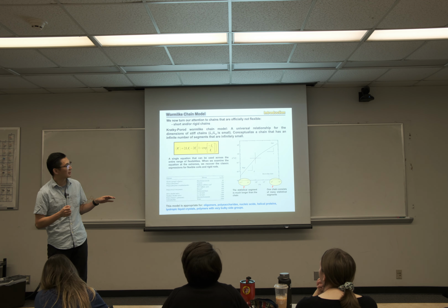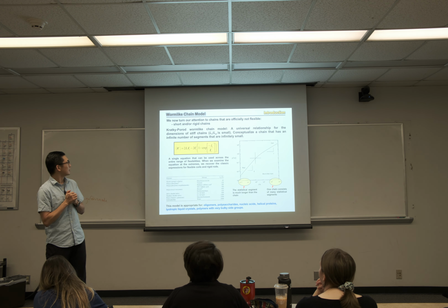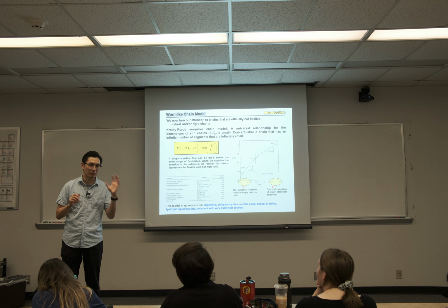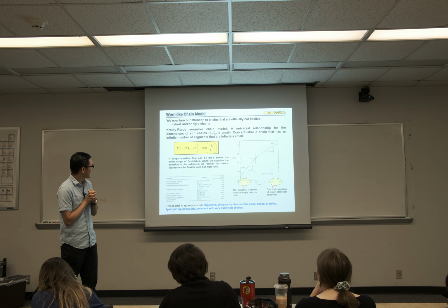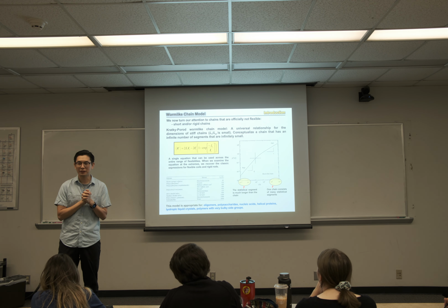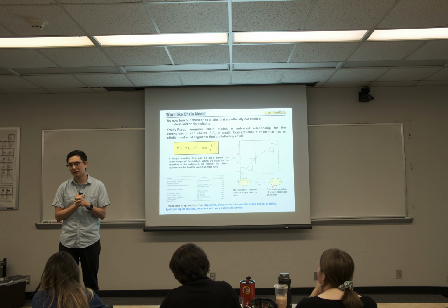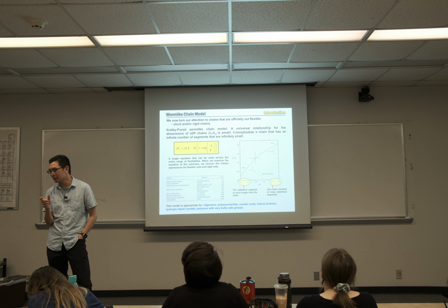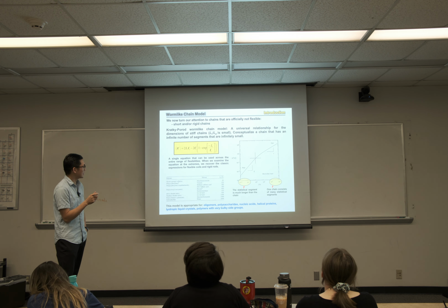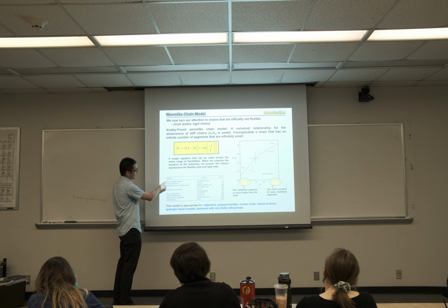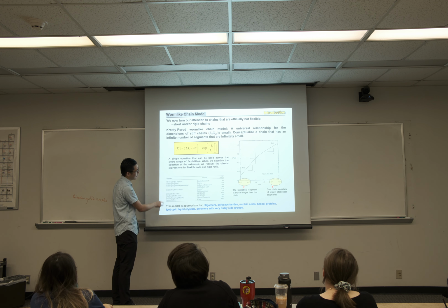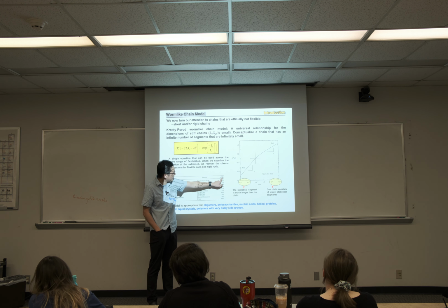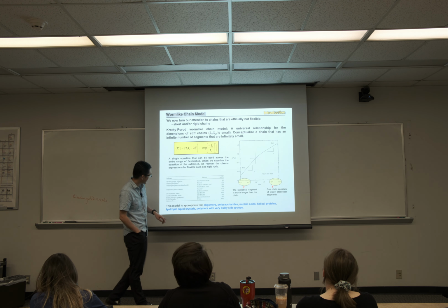So we have a little bit left uncovered: the worm-like chain model. This is something I want to wrap up before we talk about radius of gyration. So what is a worm-like chain model? Everything we talked about in the last lecture is based on chains that are reasonably flexible. But there are also chains that are not so flexible. These are a few examples we showed here. You can see the persistence length LP can go anywhere from 65 angstrom all the way up to 200.